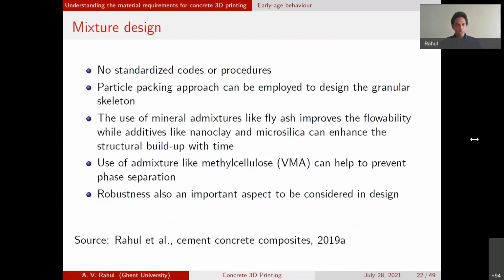Now just to give a few words on the mix design as well. As you could imagine, there are no standardized codes or procedures for designing printable concrete. But one of the ways we could try to do this is by using the particle packing approach. Using the particle packing approach, the granular skeleton can be designed. But when you design the granular skeleton, we need to make a choice of different mineral admixtures. Unlike conventional concrete, a key parameter that we have to keep in mind is how these mineral admixtures might influence your early age behavior, especially in terms of how quickly the material starts to set, how it influences the yield stress, and how it influences the viscosity.